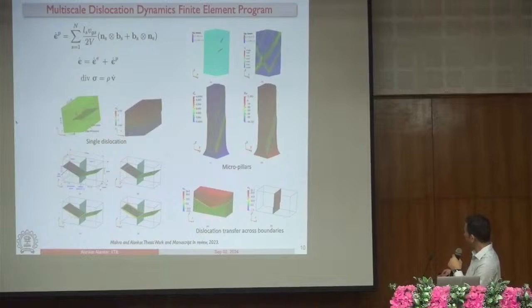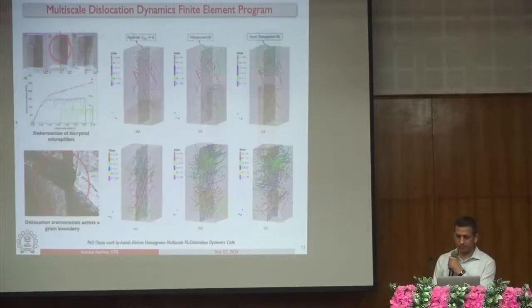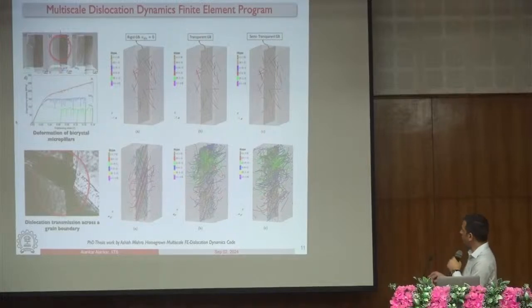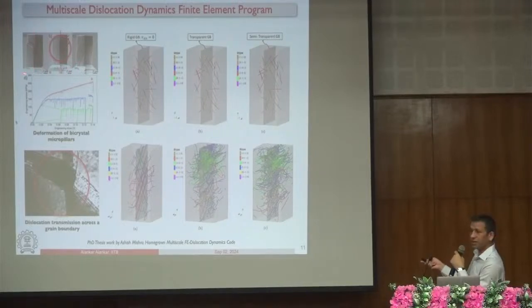This is an example of grain boundary and dislocation interaction where the dislocation has come from the left side and it has crossed the grain boundary. And because the dislocation has crossed the grain boundary, there is a small step at the boundary. That is called residual Burgers vector. These are some of the more complicated simulations using the same tool called dislocation dynamics. These are bicrystal pillars. These two single crystals have been joined along the diagonals.